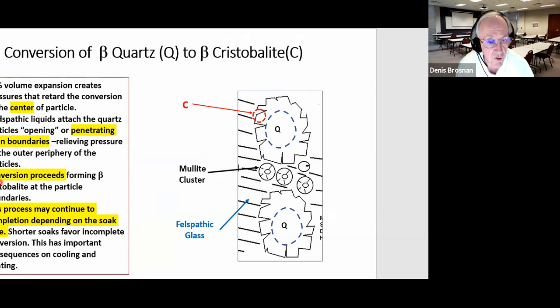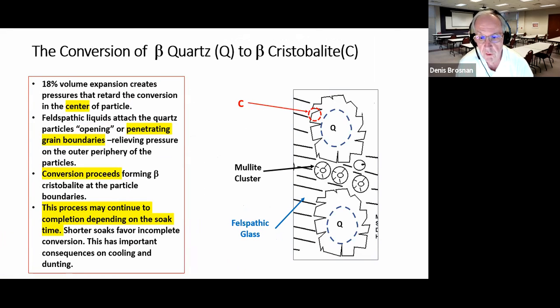You'll recall that last time I also talked a bit about the conversion process for quartz. In this situation, I showed you the feldspathic glass and the mullite in this little diagram with a relic of what originally was potter's flint or quartz crystals. The conversion of quartz, beta quartz to cristobalite, occurs along with the attack of the feldspathic liquid on the grain boundaries in this polycrystalline quartz. As they open up, that releases a little bit of the compressive stress that's developed within the particle, and the cristobalite readily forms. Then we get very little tridymite in this situation.